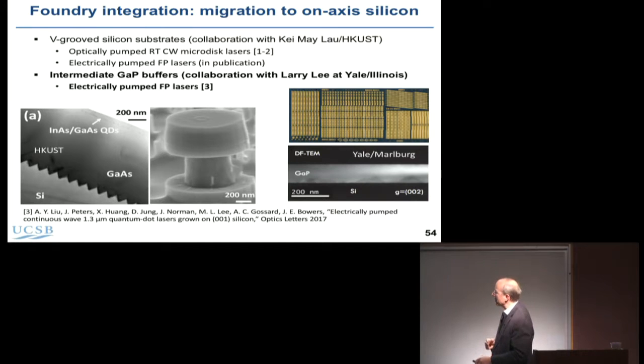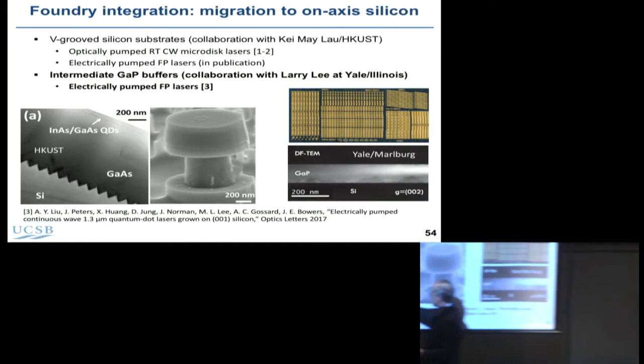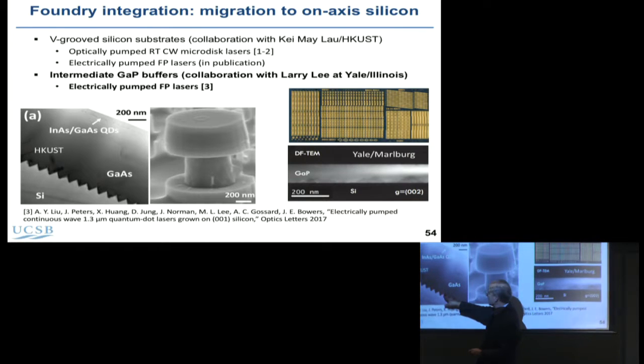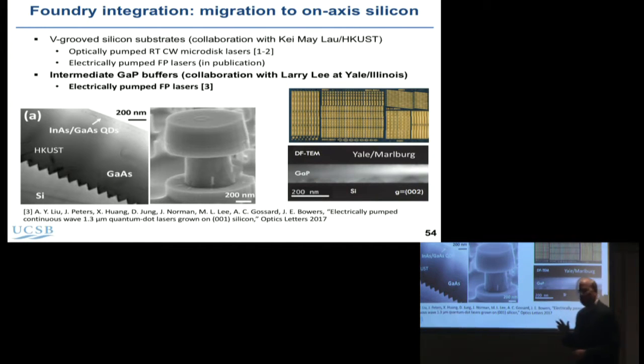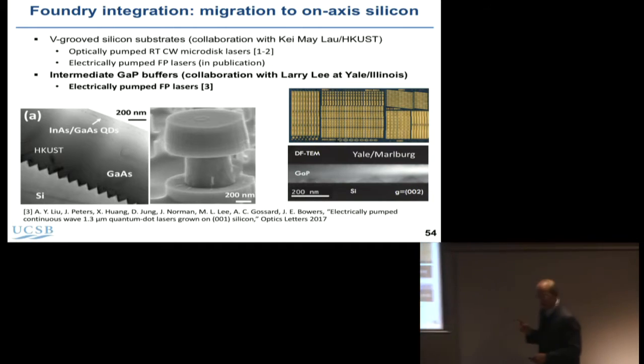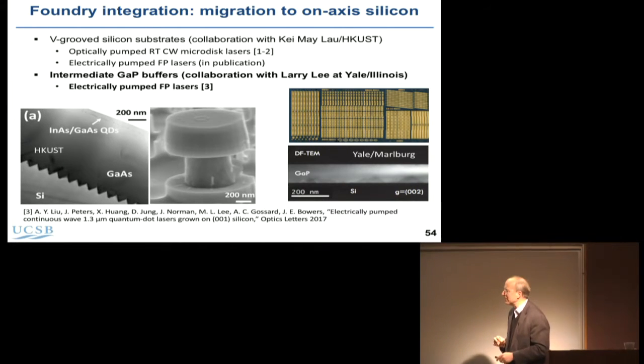The reason that works, you can't really see it too well here, at least I can't, is that the stacking faults and dislocations propagate up along these 1-1-1 faces and typically terminate at this point. So the dislocation and stacking fault density down here is very high, but up here it can be quite low. The results I'll show in a second are about 10^8 per square centimeter. But we now have structures at about 10^7 per square centimeter. So our hope is that with 10 times lower dislocation density we can get better results.